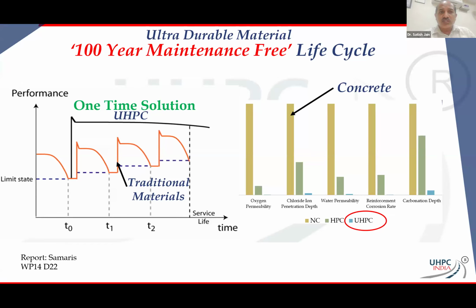Yes, maybe the initial costing here or there might be a little bit higher, but in the long term, believe me, the country is going to save immensely, and that money can go into various other things, in fact. So the right side just shows a unit comparison between concrete, high performance concrete, and in blue, if you can even see it on your screen, that's UHPC. So this is with regards to permeability, chloride ion penetration, and corrosion rates and carbonation rates. You can see that UHPC is way, way, way lower than concrete. And that is again the reason that you get that 100-year maintenance-free life cycle. So that's the beauty of UHPC.